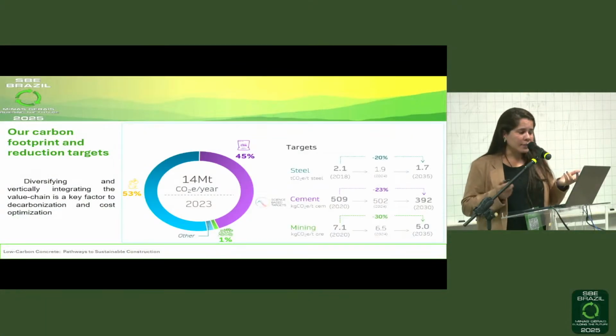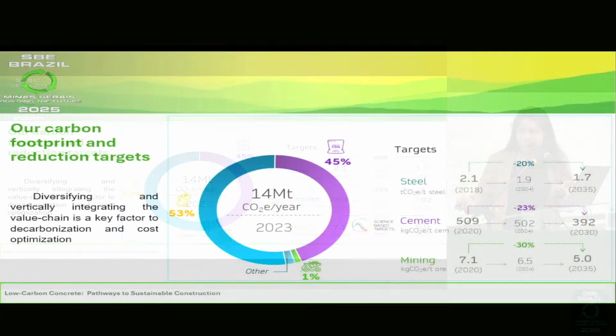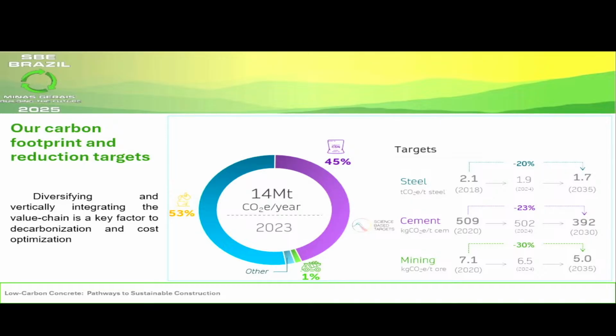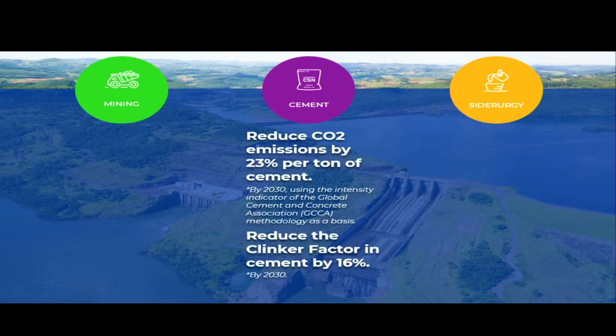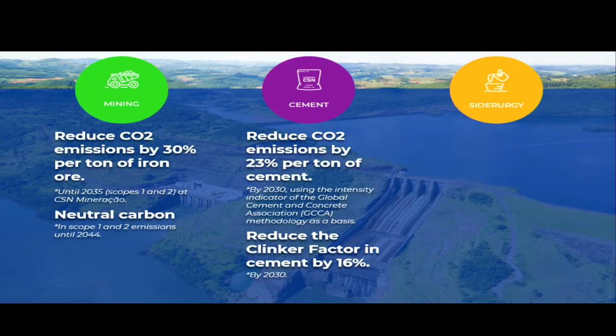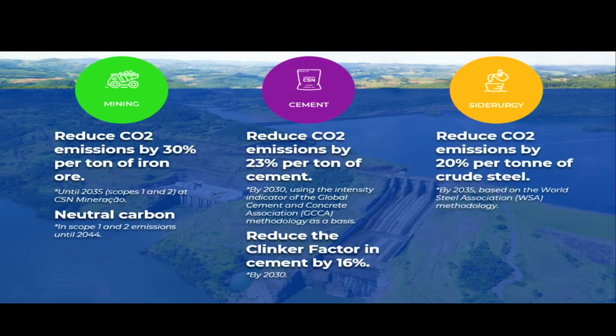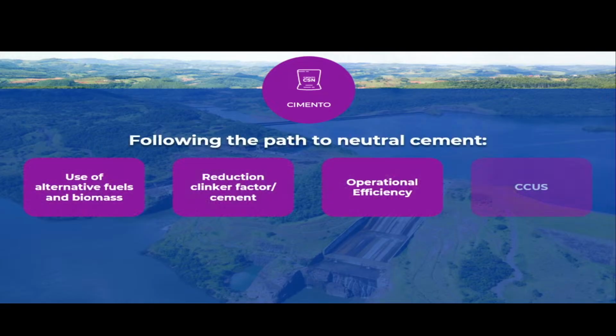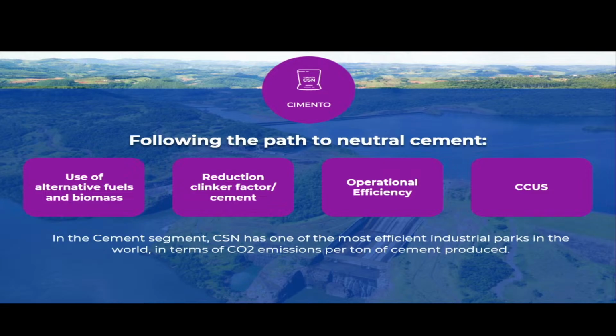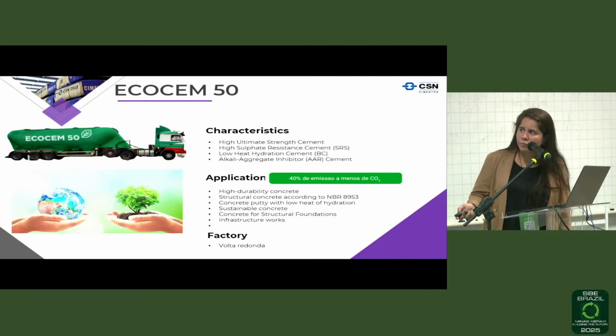This is important. We also need to account for the whole production chain, even for the material that is applied. And the CSN has its own goals that are important for steel, for cement, and for mining. So we have the goal of reducing emissions 23% per ton of cement by 2030, and a reduction in the clinker factor in cement by 16%. We also have a goal from mining and siderurgy. In cement, we are using alternate fuels and biomass. There is a reduction in the clinker factor in cement. We have operational efficiency and work with CCUS as in carbon cure.